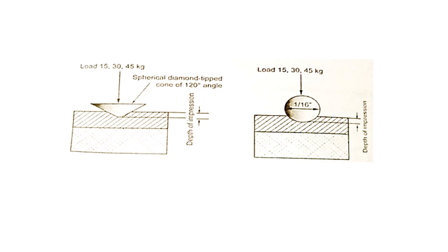Minor static load: a 3 kg minor static load is applied to form a very shallow indentation on the surface of the specimen through the compression of a calibrated coil spring placed within the machine between the indenter shaft and the dial. The purpose of applying minor load is to eliminate the error that may arise due to variable contact between the indenter and the surface of the specimen, to set the indenter on the specimen and hold it in position, to eliminate the error that may arise due to slight surface imperfection, that is, minimize the surface preparation of the specimen, and to reduce the tendency for ridging or sinking in caused by the indenter.